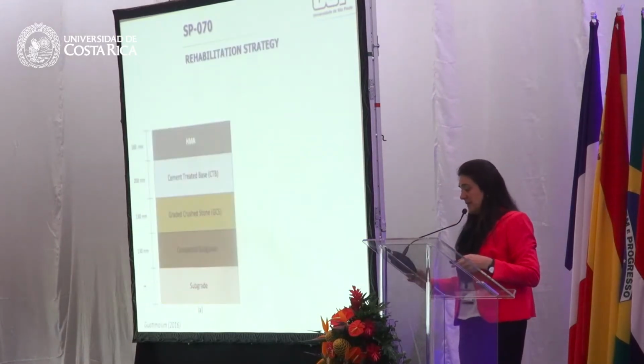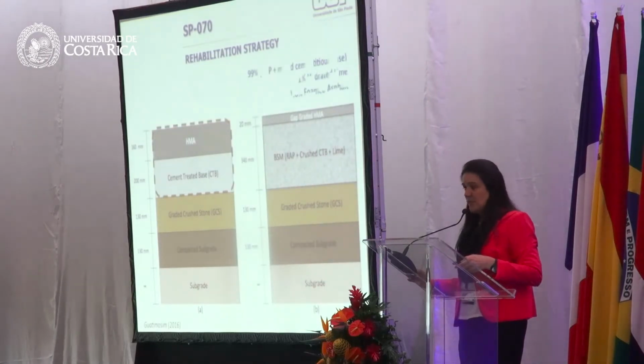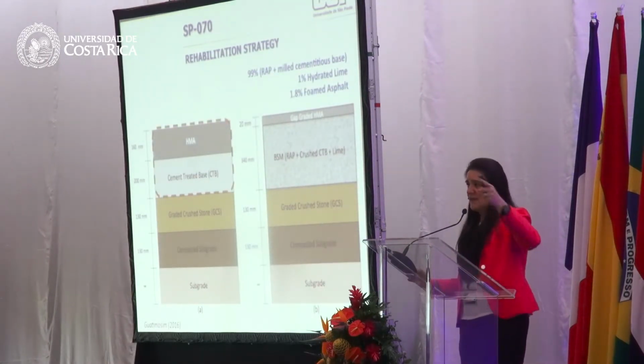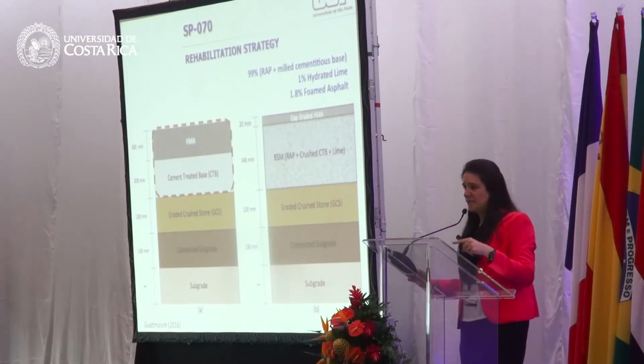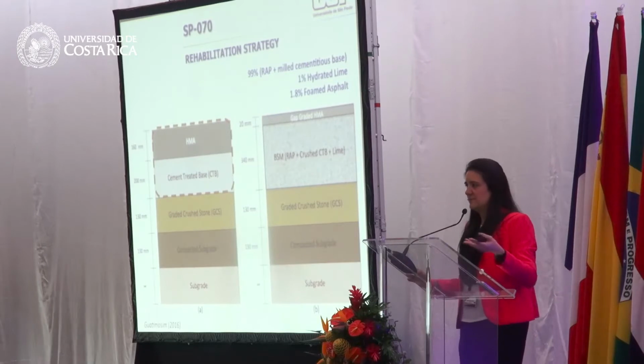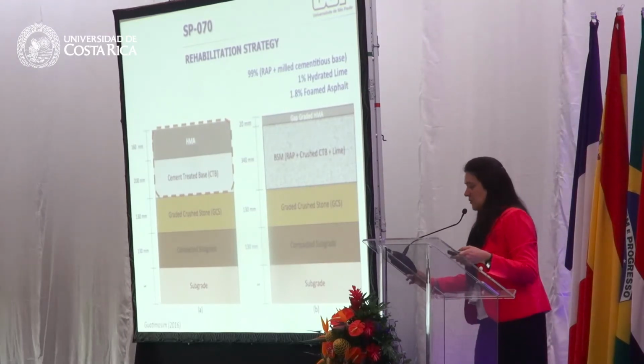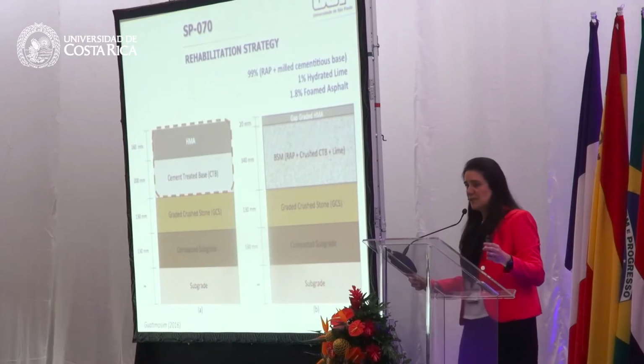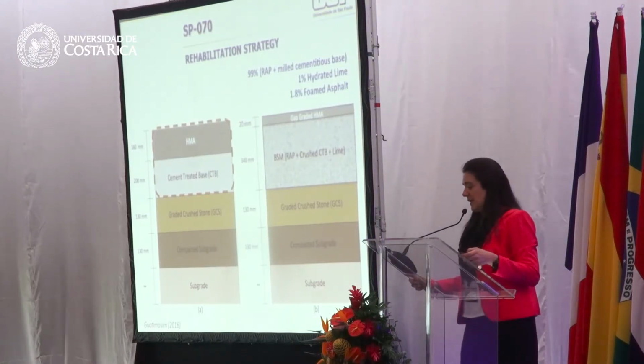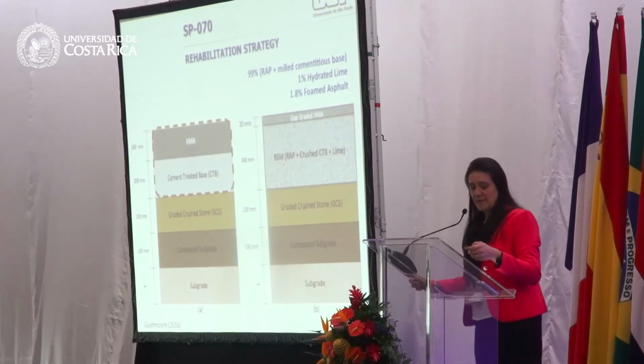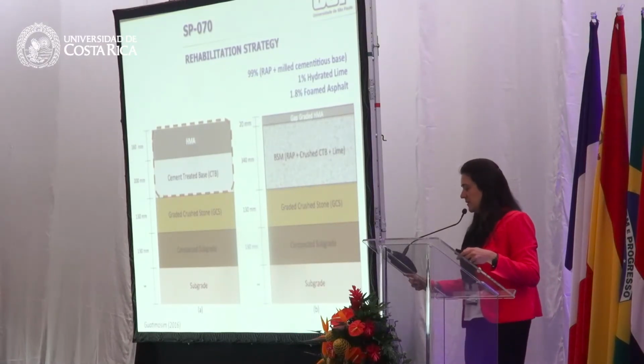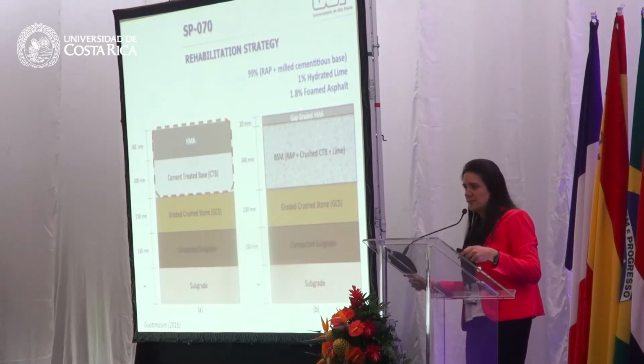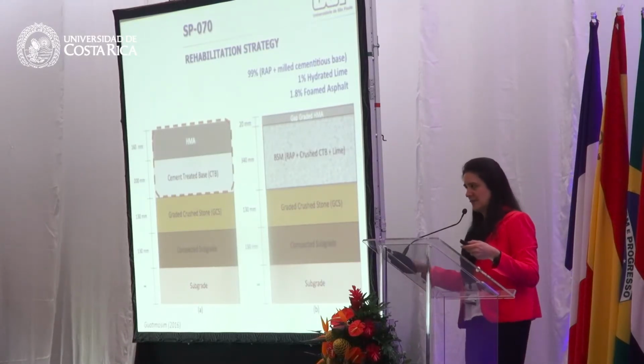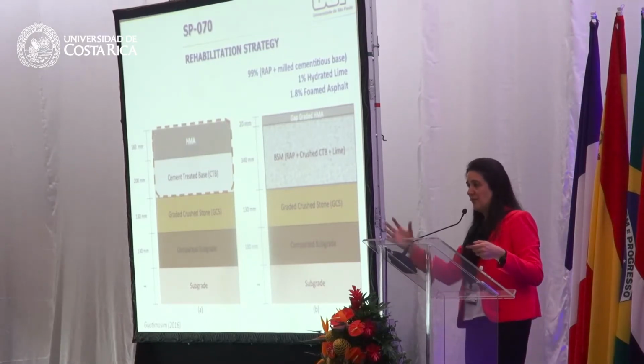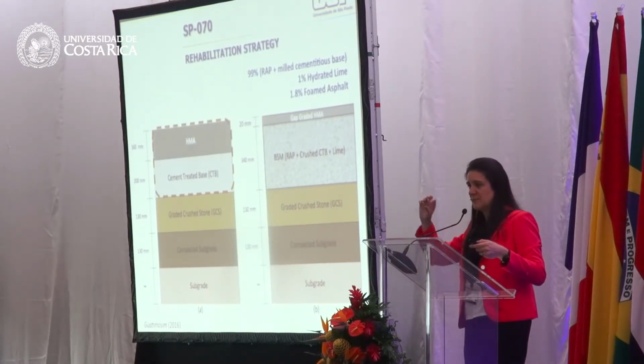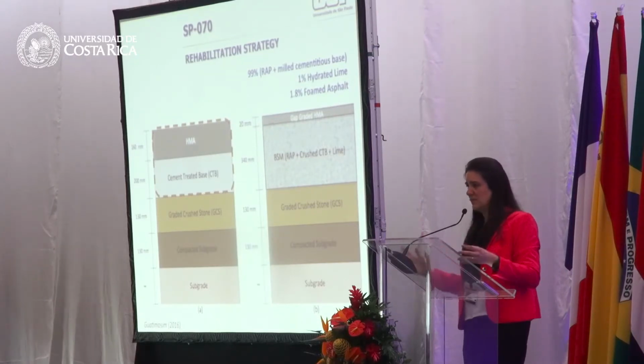So the rehabilitation project was, let's remove, because they had tried milling and putting some new HMAs, and it didn't work, of course. The base layer was completely cracked. So at a certain point, okay, let's do it in a right way and remove both layers. So the rehabilitation project was 34 centimeters of BSM, bitumen stabilized material, RAP, plus at this job site, we had the foaming process with the RAP plus the recycled aggregate from the base, all mixed together.